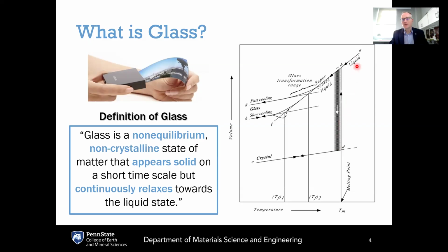And if this liquid, after it crystallizes, continues to cool, then it will follow this crystal cooling line going from point D down to point E, and the crystal will contract according to its thermal expansion coefficient. You'll note that this has a lower slope in the crystalline state compared to the liquid state. That indicates that the thermal expansion coefficient of the crystal is lower than that of the liquid.